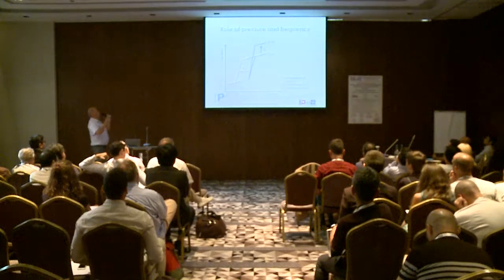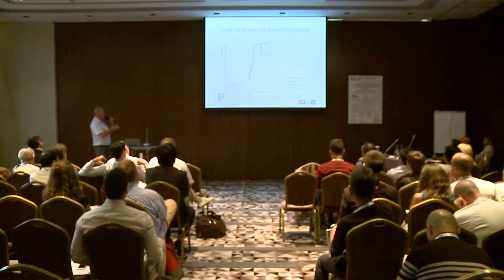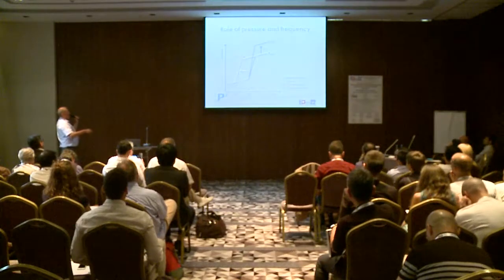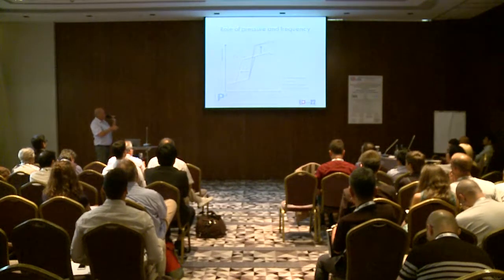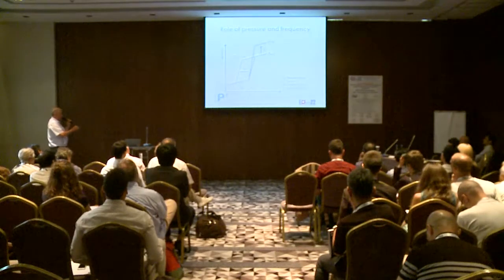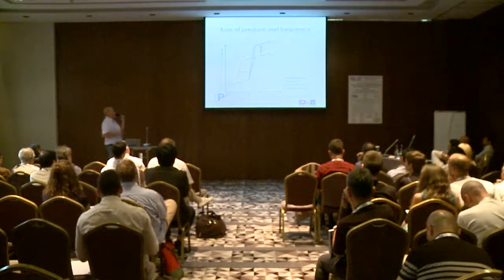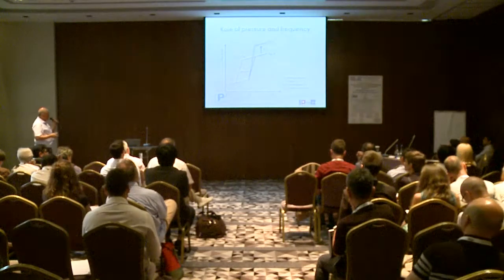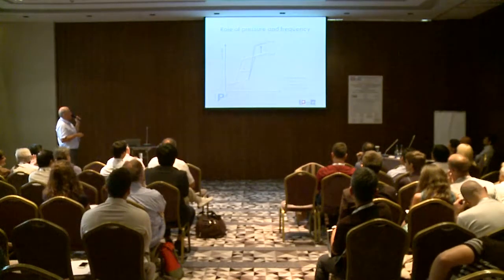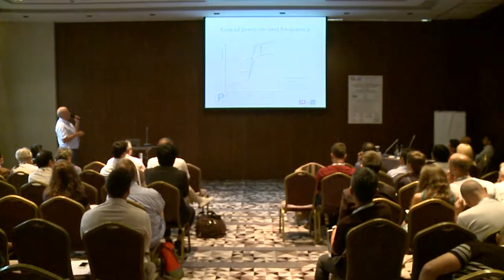We also performed additional experiments by making the pressure vary and also the frequency. The results are summarized in this graph. Basically, the pressure will influence the transition regime. If you increase the pressure, the transition is observed at a lower value of delta K. And for a given pressure, if you lower the frequency, you increase the fatigue crack growth rate in the highly accelerated regime. But nevertheless, in all cases, you have three regimes: Regime A, where we have no fatigue crack growth enhancement, a transition regime, and then a highly accelerated regime.